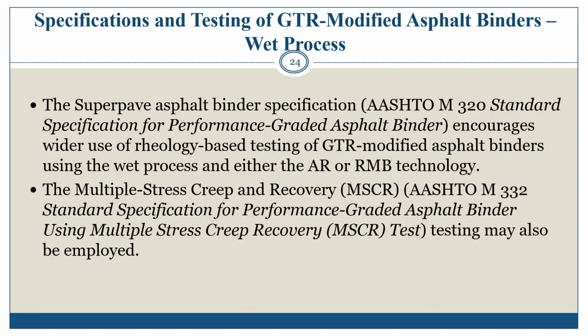Specifications and testing of wet process GTR modified asphalt binders. AASHTO standard specification M320 and M332 may be employed for wet process GTR modified asphalt binders. Modifications to dynamic shear rheometer methods such as increased gap and concentric cylinder geometries have been used to address GTR particle size effects. Increased gaps and alternative geometries allow adherence to the standard specification.